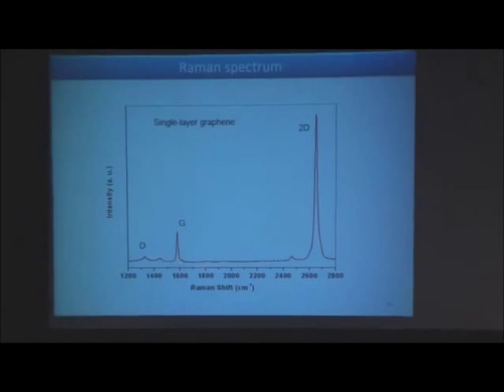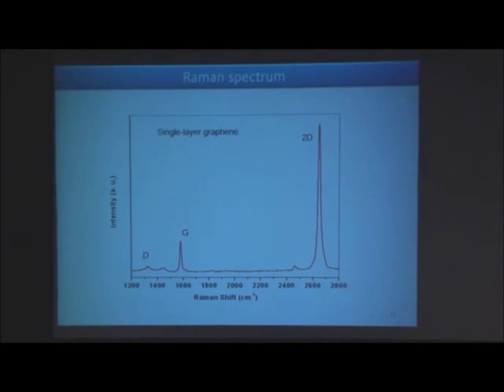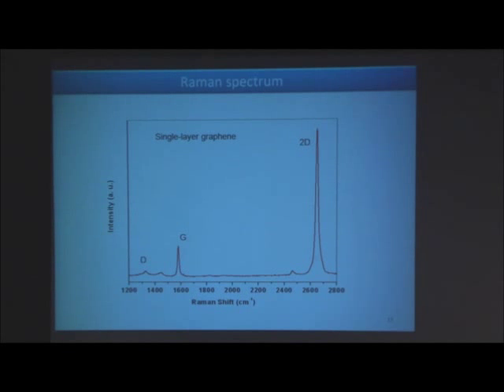In graphene, there is no other spectroscopic signature. You see, in the case of nanotube, we had two signatures. One was Raman, another was the electronic spectra, electronic transition. You could see that. Here, there is no electronic band of graphene worth mentioning. So this is very interesting. You see, a single layer graphene gives a G band, which is not very intense. That is the most primary band of graphene, sp2 carbon, the sp2 carbon vibration, skeletal modes, tangential mode.